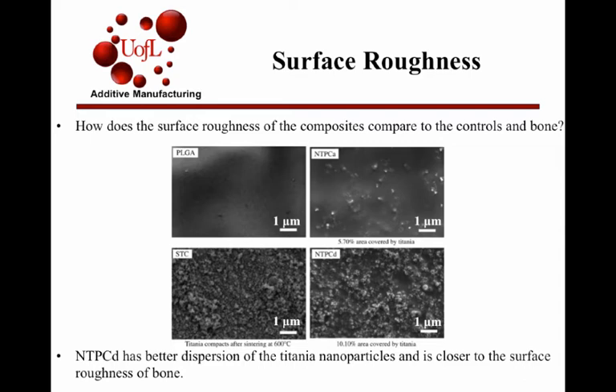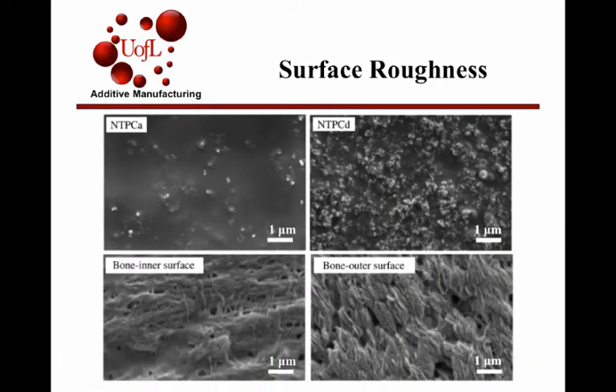The next slide shows another comparison to bone. But the main conclusion was that the dispersed composite, so they had higher mixing power, had a closer surface roughness to the bone, which is the goal of the study. And this is that comparison. The top left is the agglomerated, and the top right is the dispersed, and then the bottom are two images of bone, and they're all at the same scale. You can see that the outer surface is fairly rough, and the agglomerated NTPC was quite smooth. So they wanted a little bit rougher surface, and they chose the dispersed. In the paper, they also showed the standard ceramic by itself, and it was far rougher than the bone surface, so that wasn't as desirable.